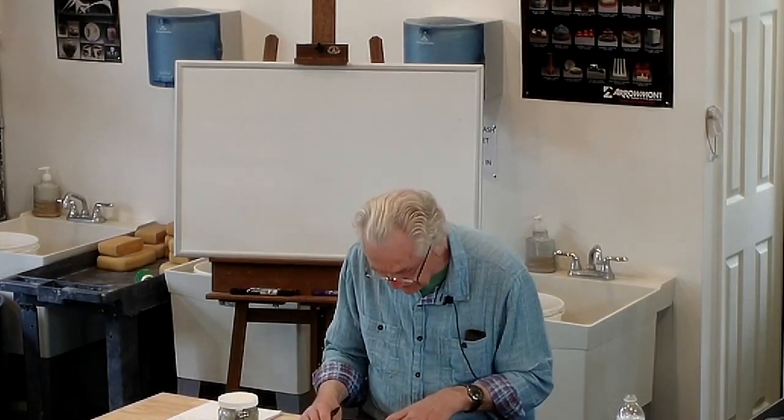On the left-hand side of the first page, here's a really simple glaze recipe. A Ravenscrag clay slip is just a naturally occurring, highly colored clay. It's kind of like Alberta slip or Albany slip. This is a cone 6, cone 7 glaze, with a little bit of frit and clay and silica. And they've added titanium oxide to make it a little more opaque. Very simple.